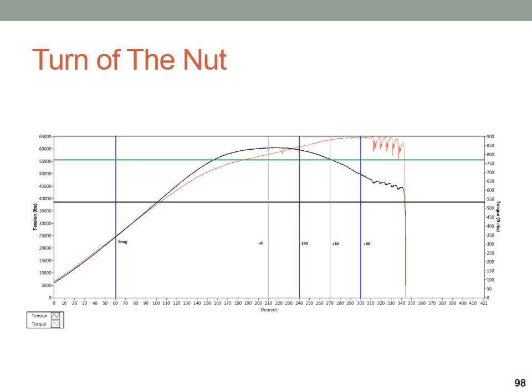Again, the turn of the nut method, a lot of people don't completely understand it. It's pretty simple, right? You snug tight, turn X number of degrees, and you're essentially guaranteed some level of tension. The problem is all of the criteria for snug tight were established essentially starting at low or no tension, and we know that very few connections actually start like that. In fact, in most cases, again, this is an example of that torque tension angle curve that I mentioned earlier.